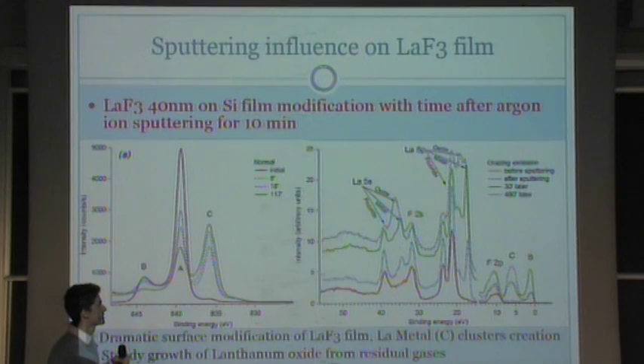another part of the spectra, the valence band, and here you can see that at the beginning it was clean lanthanum fluoride, the red curve, but after sputtering there are metallic features here, here, and here, and after 30 minutes and 500 minutes, it's oxidized, so you've got oxygen features.